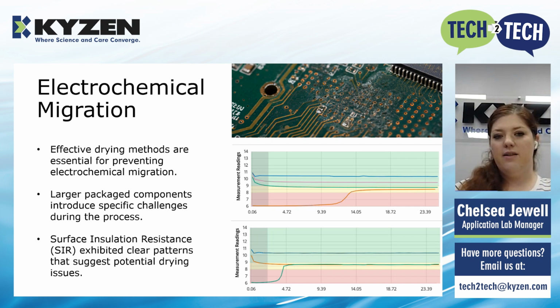This is an instance where there was moisture trapped underneath the component. And while that area doesn't completely recover up into an acceptable level, there is a noticeable shift where it's coming back out online there. So looking at troubleshooting your drying process, an SIR test may be a really good test to be able to flesh out what you're doing there.